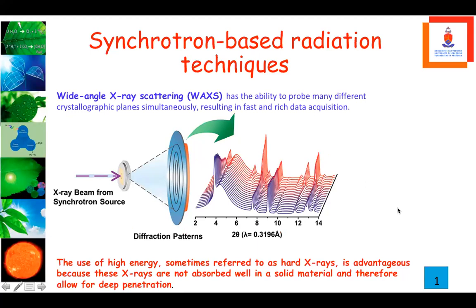The first technique that I want to just highlight here is the wide range X-ray scattering technique, which has a great ability to probe many different crystallographic planes together, resulting in a fast and rich data acquisition. And this picture here shows your X-ray beam at the synchrotron source, and then diffraction patterns that are created with a wavelength of about 0.3 angstrom. The use of high energy, sometimes referred to as hard X-rays, is advantageous because these X-rays are not absorbed well in a solid material and therefore allow deeper penetration.